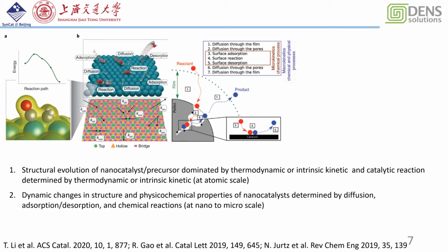This catalyst is several dozen nanometers to 100 nanometers, and it has pores, channels, and defects. In that case, the diffusion of the reactant inside the catalyst, adsorption, and many different chemical processes heavily influence the catalytic reaction. And in that case, we cannot use that to examine the fundamental catalytic reaction steps.